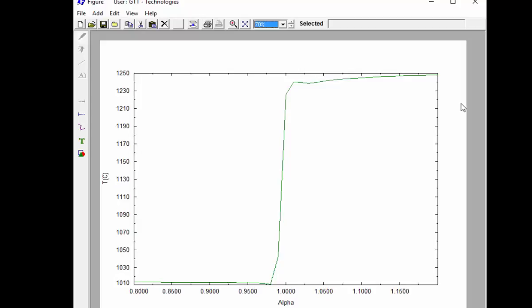Thus, the complex thermodynamic equilibrium calculation can be directly used, for example by a power plant operator, to see how operation conditions have to be tuned to avoid deposit buildup when changing the coal and hence the mineral additives. If we want to better understand the reason for the difference in slag formation temperature, we can look at the composition of the slag.